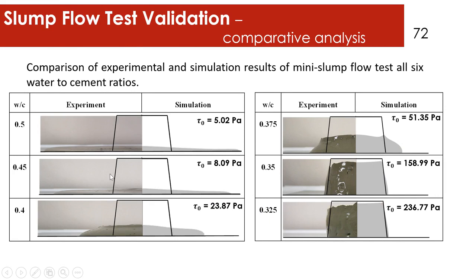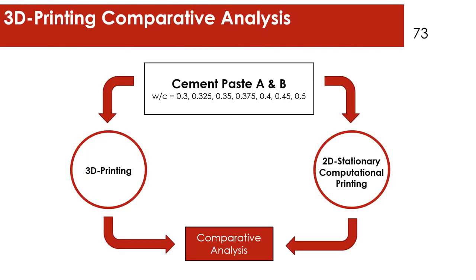And you have on this side the actual slump behavior of real cement, and on the right side the slump behavior from our computational model, which was derived from rotational shear rheology, flow rheology measures, with no calibration against the actual slump. And we get beautiful agreement between the two.